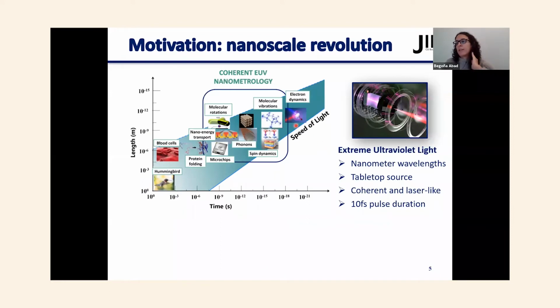So, when we want to characterize features in the nanoscale, we really need to go also to the ultrafast times. In features at nanoscale sizes, we can find phonons, spin dynamics, molecular vibrations. So we need to go from nanoseconds to femtoseconds. And we happen to have this very useful tool based on extreme ultraviolet light, which is created by high harmonic generation, and it has nanometer wavelengths. It's a tabletop source, so it's available 24/7, and you don't need to go to a big facility to do experiments. It's also coherent and laser-like, and the pulse duration of these beams is as short as 10 femtoseconds, so you can really do very well-resolved in-time experiments.